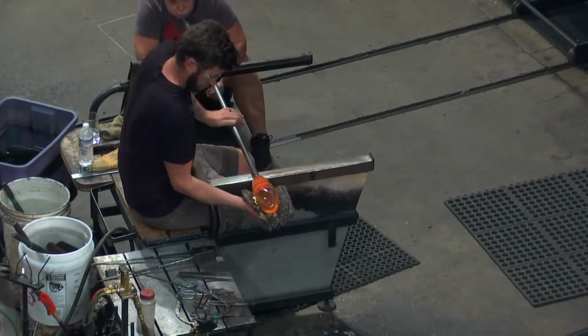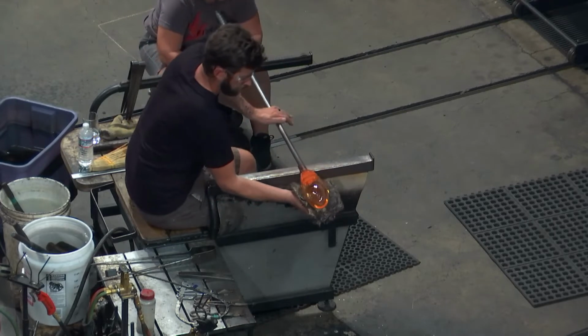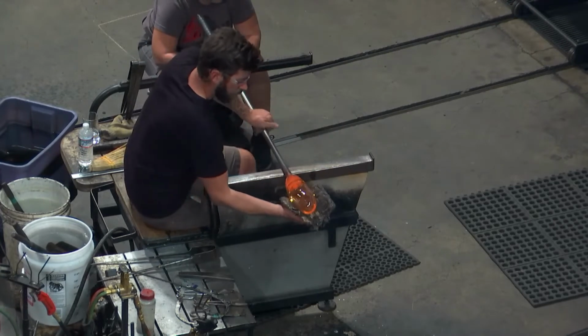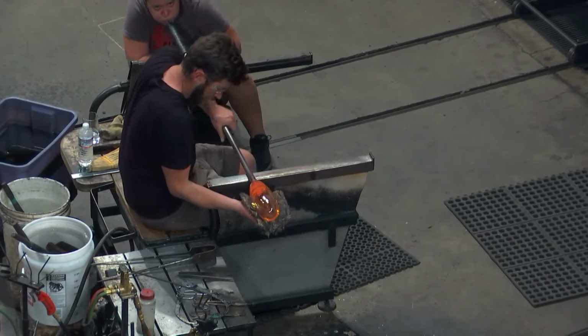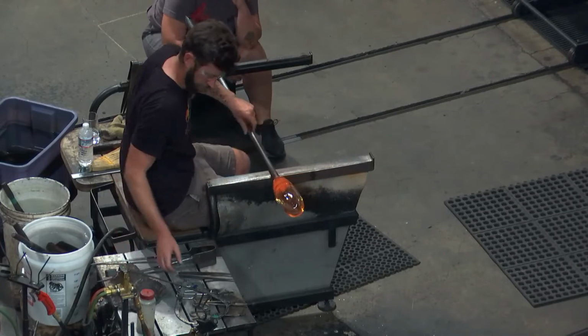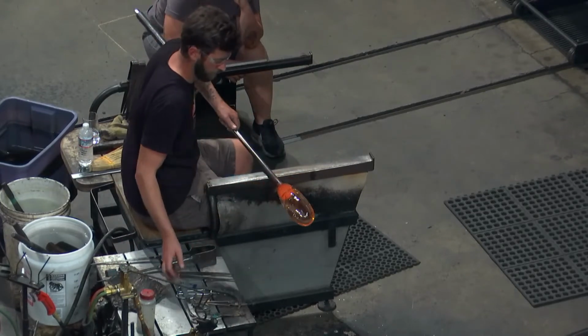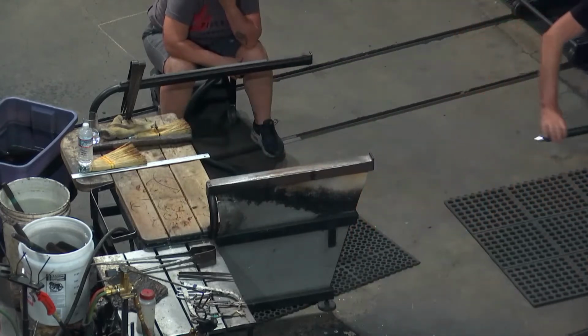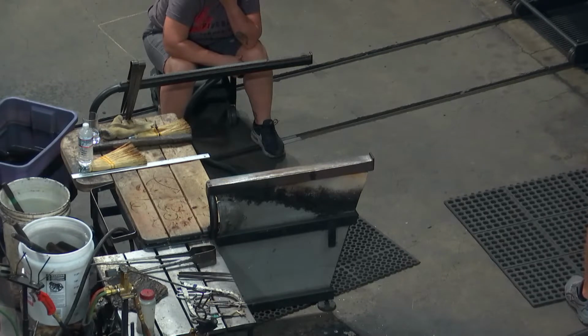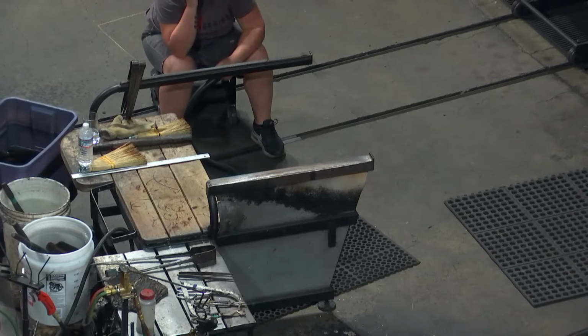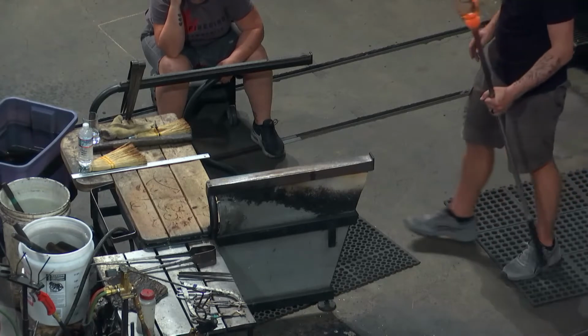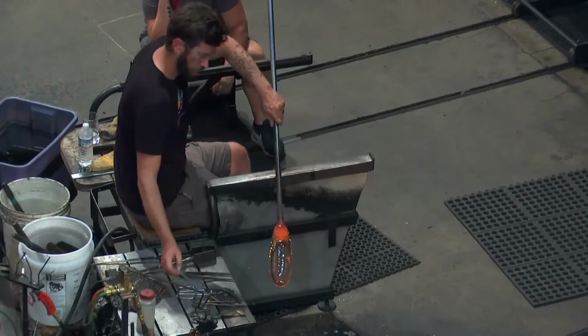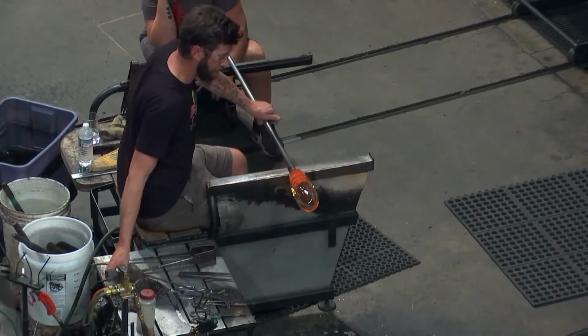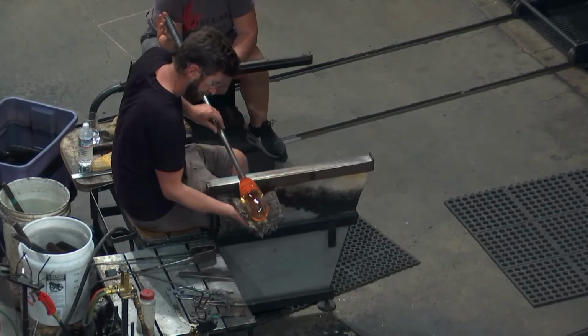So as Sarah blows into the end of this pipe, as she exhales, she enlarges that bubble, and Ben has papers in his hand, and the papers allow him to basically sculpt that glass with his hand without getting burnt. The papers are rolled up newspaper soaked in water. When the cold water meets the hot glass, the thin layer of steam is the protection. It leaves minimal residue on the glass from the papers, because of course if we put dry paper on 2,000 degrees of hot glass, it would just instantly catch fire. So we use water.